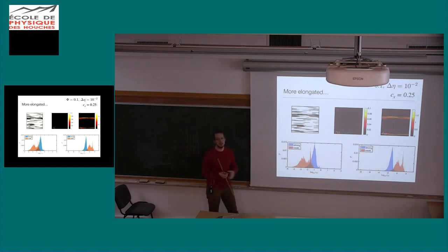So in that case, when it's elongated enough, you just form this percolating cluster, and then the properties of that cluster control everything. This is actually something that depends a bit on how big you make your box. So you have some finite sample effects when you form this. The numerics just get to a limit, because you can make your box bigger and bigger, and then maybe you won't connect from the left to the right side.